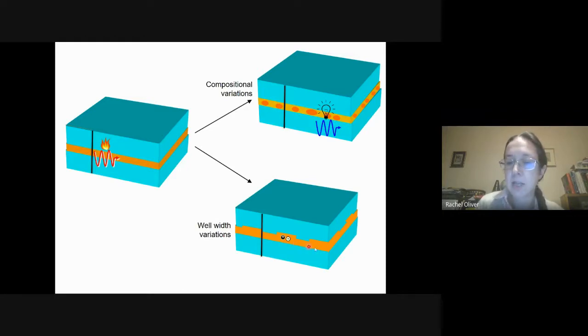That's because in very small structures, we saw these in the LED, we saw in the TEM only about 2.5 nanometers thick. In those very small structures, the available energy levels are quantized depending on the thickness of the quantum well. And those quantization energies drop, and we have a lower energy state in the thick part rather than the thin part of the quantum well. So the thick bit can also act to trap the electron and hole, so they can't move around and get to the dislocation, and so they tend to recombine to emit light rather than heat.